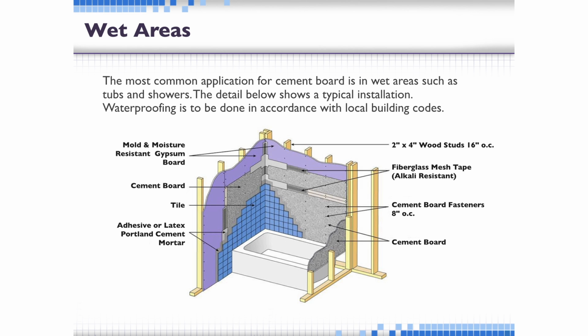So, quick and easy, you can actually put the cement board right to the studs. We treat the joints of our cement board, as you saw those samples, they're almost tapered edged like drywall. I mean, they do have a little bit of a tapered edge to them. So you fill that with whatever you're sticking the tile with and a 2-inch wide fiberglass mesh tape, which anybody sells. You don't have to use ours, you can use anybody's you want. And then just embed that with whatever you're setting the tile.